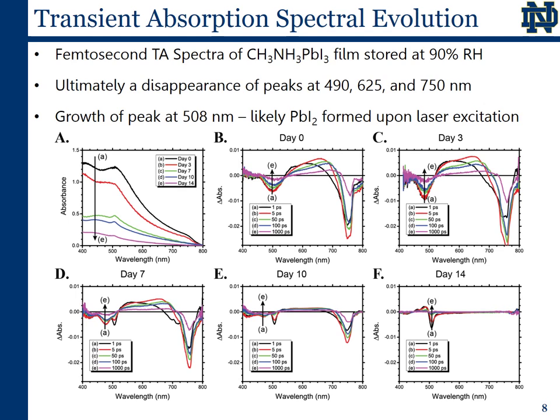While methylammonium lead iodide films exposed to moisture in the light can form PbI2, we do not find any evidence for crystalline PbI2 when these same films are exposed to moisture in the dark. It is therefore likely that some small amount of lead iodide is formed in the present case when the degraded perovskite films are exposed to laser excitation during the course of the transient absorption experiments.